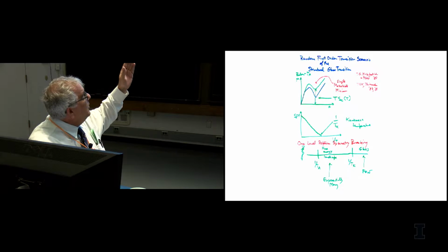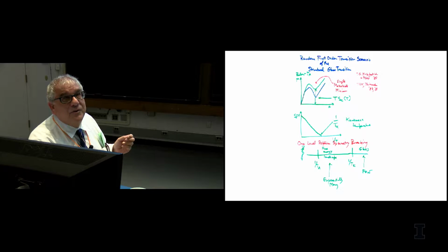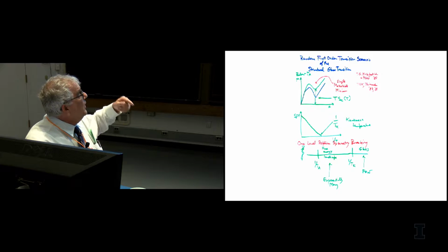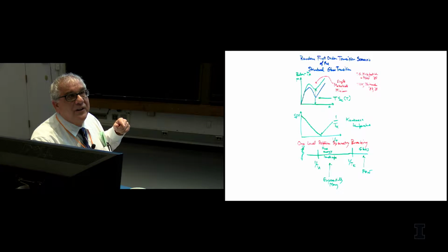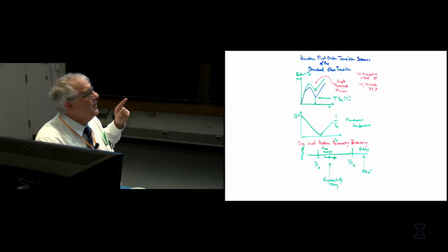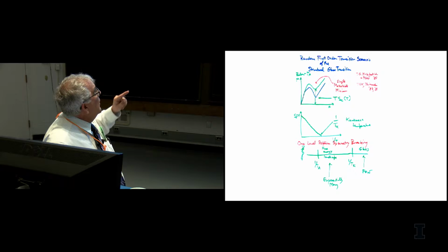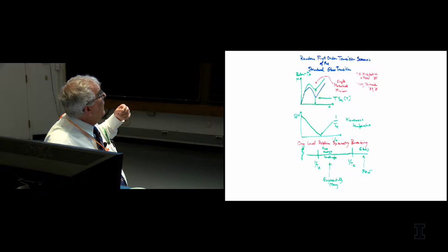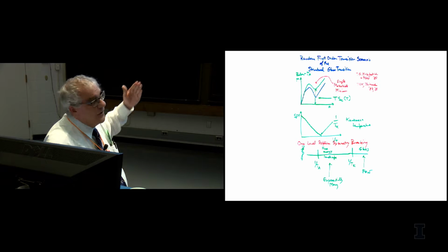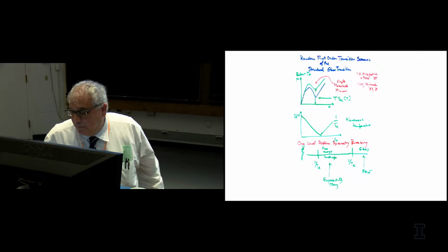And what you find is that entropy is going down and down and down as you cool below. And it would seem that there would be a temperature at which that entropy would go to 0. Well, in that case, even though you have a disordered structure, there's only basically one of them. And so, obviously, you can't move there at all. That would be an ideal glass. So, in this picture, the glass transition is a relic of this transition that occurs when you run out of entropy.